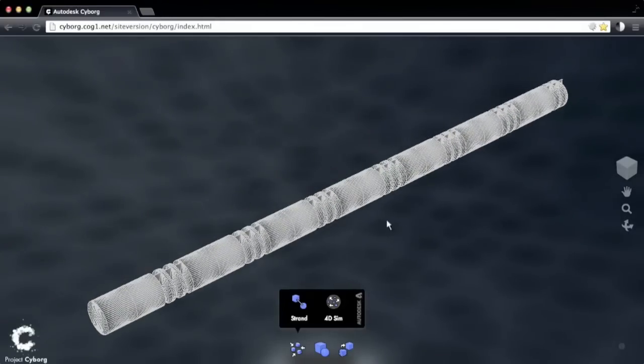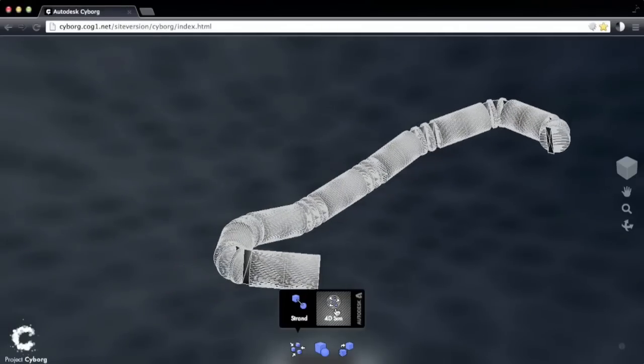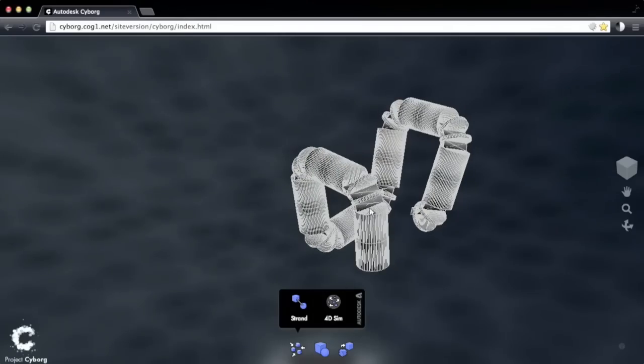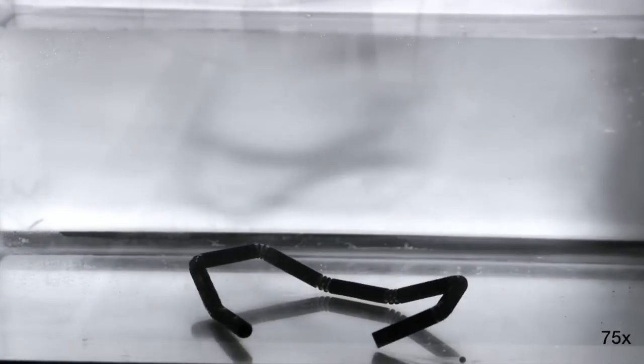We also worked with Autodesk on a software called Project Cyborg, which allows us to simulate this self-assembly behavior and optimize which parts are folding when. Most importantly, we can use this same software for the design of nanoscale and human-scale self-assembly systems. These are parts being printed with multi-material properties. A single strand dipped in water completely self-folds on its own into the letters M-I-T. Another single strand dipped in a bigger tank self-folds into a three-dimensional cube on its own — no human interaction. We think this is the first time a program and transformation has been embedded directly into the materials themselves.